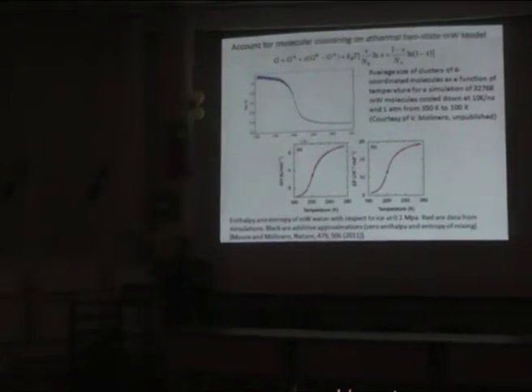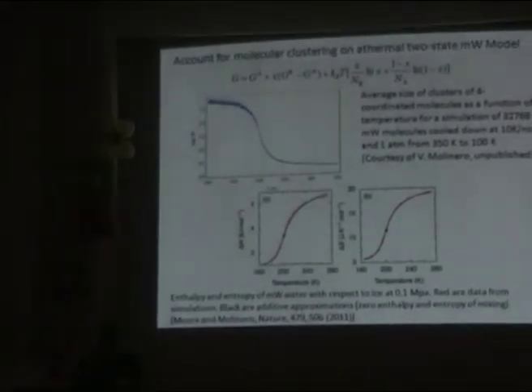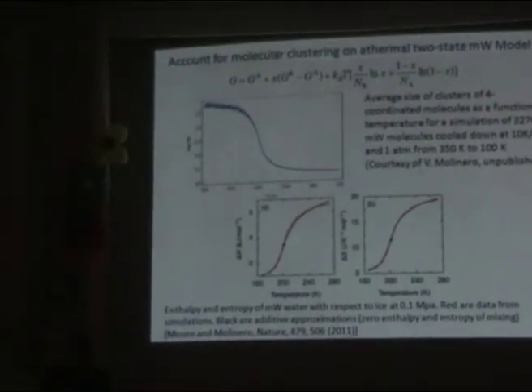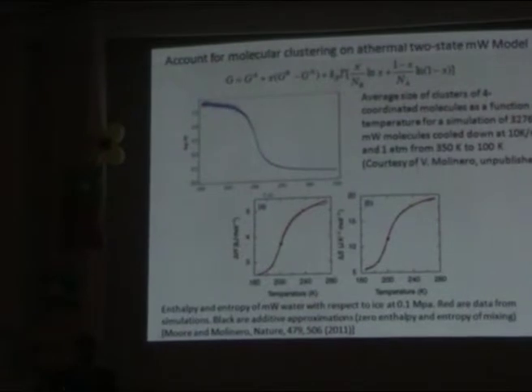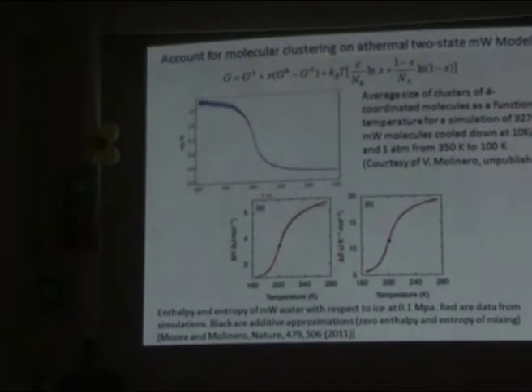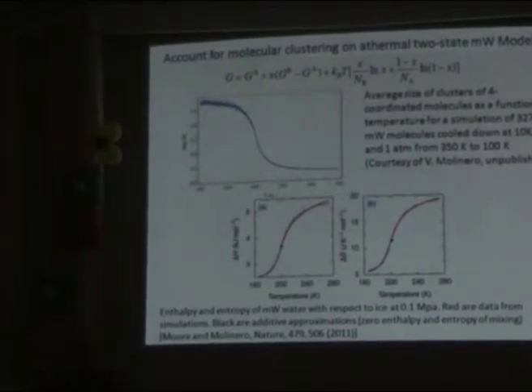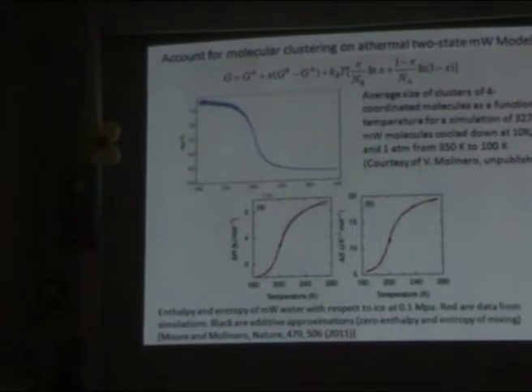What was really beautiful for this model is that Valeria Molinero directly computed the fraction of low density liquid. In our case, this is the order parameter, or extent of reaction. It is additional information in addition to response functions like heat capacity, compressibility, or expansivity. And in this case, we understand now why this model doesn't show phase separation: why non-ideality is not strong enough. The entropy of mixing is almost zero,